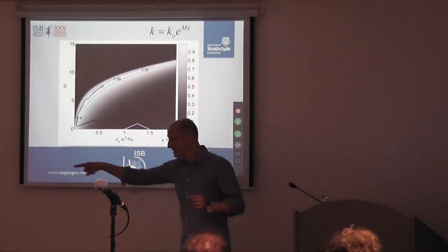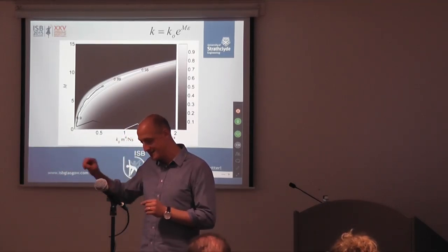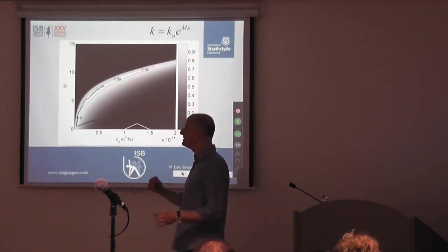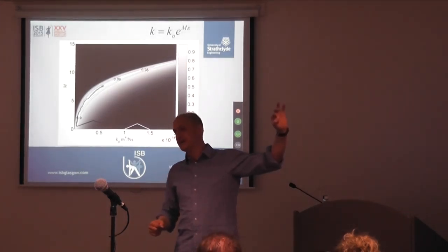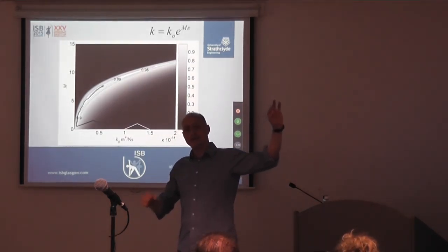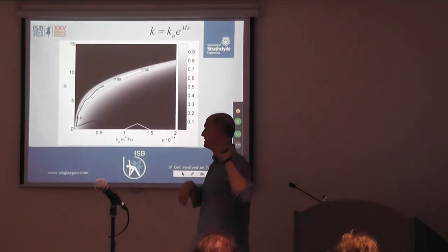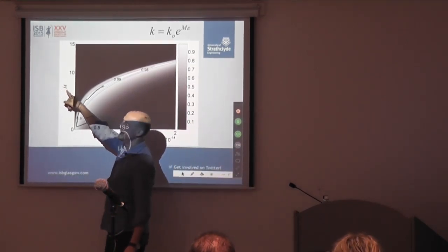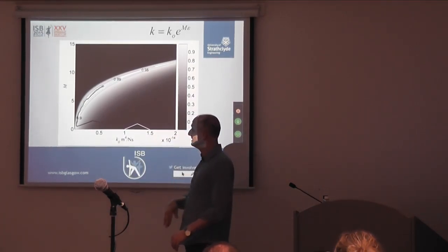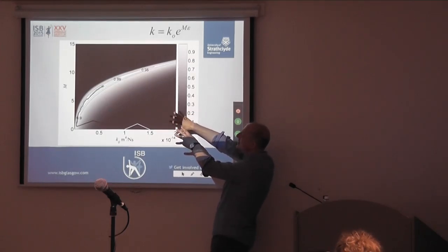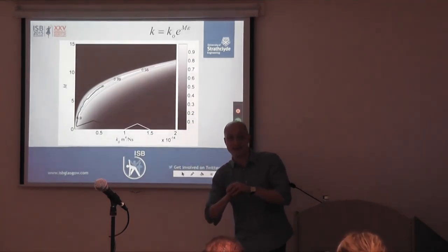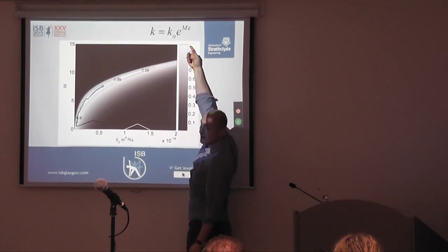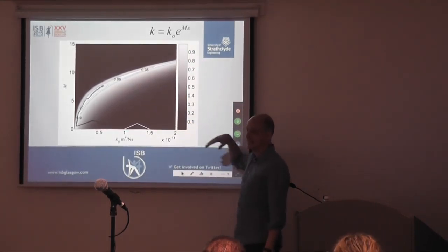And it assessed permeability. So if you can imagine a confined compression experiment, very similar to that, where you have the stress relaxation going along. And from the equilibrium position, we can predict the aggregate modulus, which is fine. And then the time dependency is dependent on the permeability. So the permeability is dependent on the initial permeability, which is at zero strain, and also the nonlinear coefficient, how permeability varies with deformation. What's been plotted here are the R squared values for that fit. So a white value here is a really good R squared value, getting up to one for a perfect fit. And black is a rubbish fit.